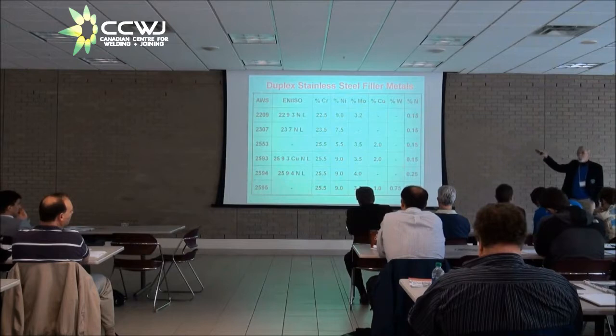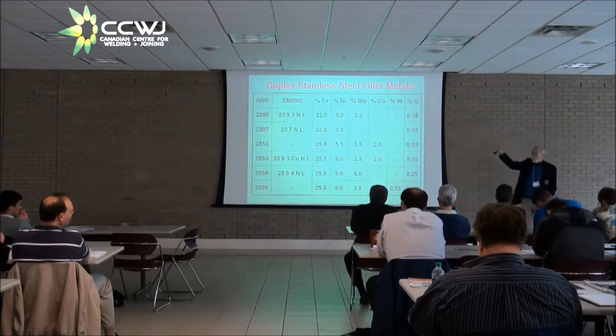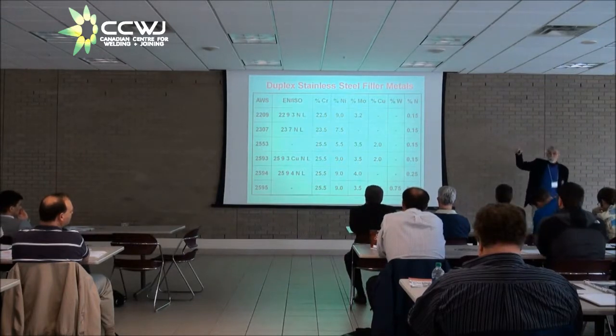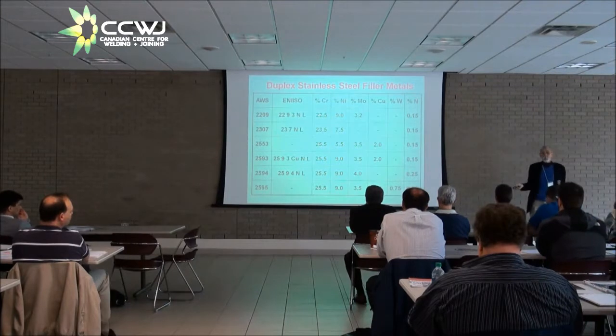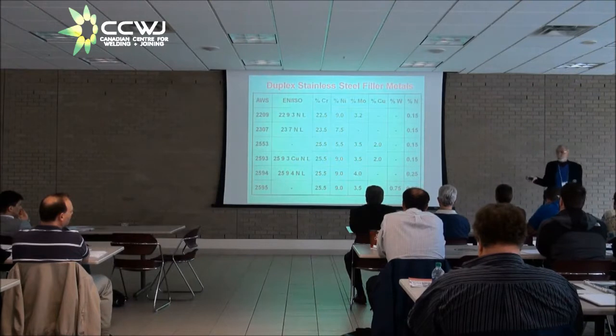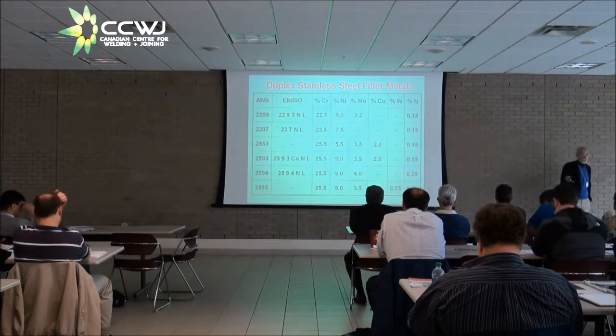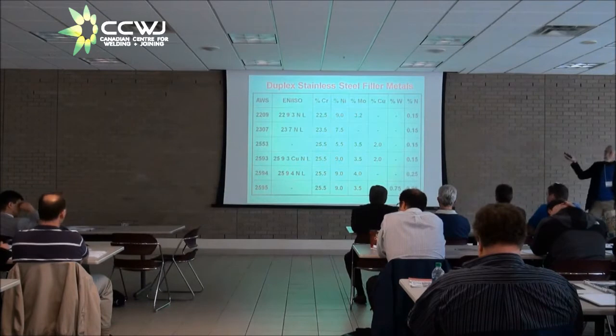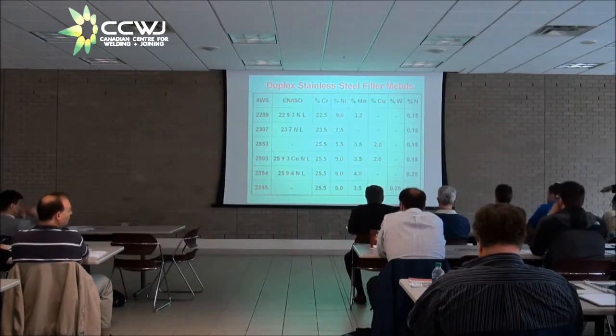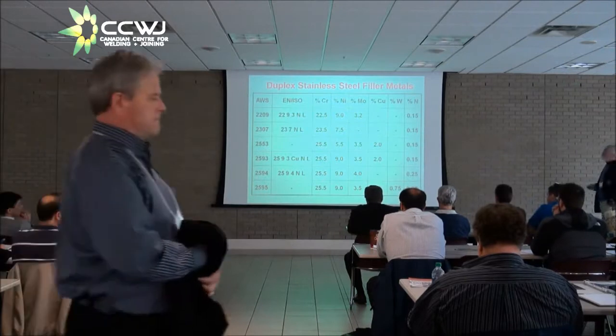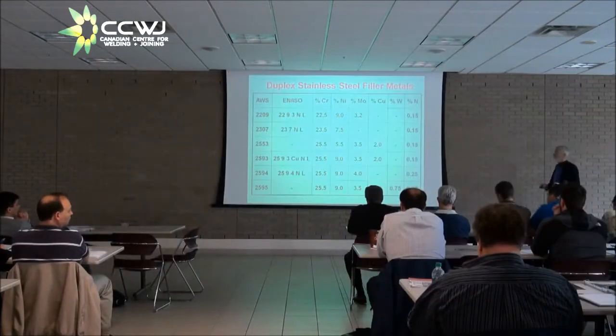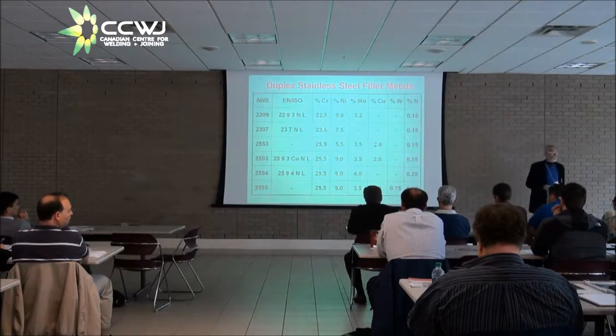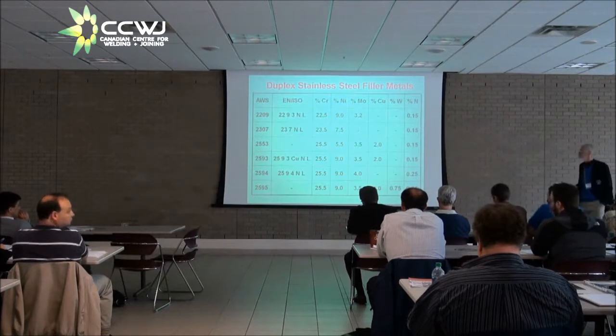The reason for that is, in the as-welded condition, if you have a 2101 composition and you pick up oxygen from a flux shielded process, you get lousy mechanical properties, in particular very poor toughness and even very poor tensile ductility. But by depending on nickel to help you out, you get better properties. So the 2307 composition, or the 2307NL as the European or ISO standard terms it, is adequate for lean duplex.